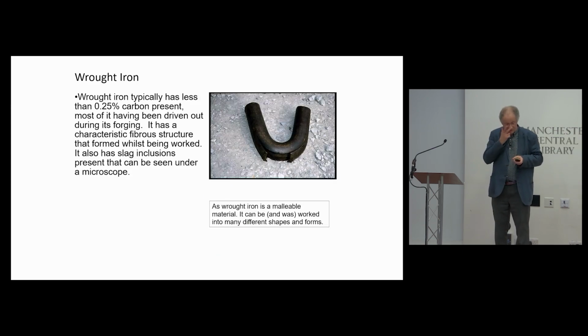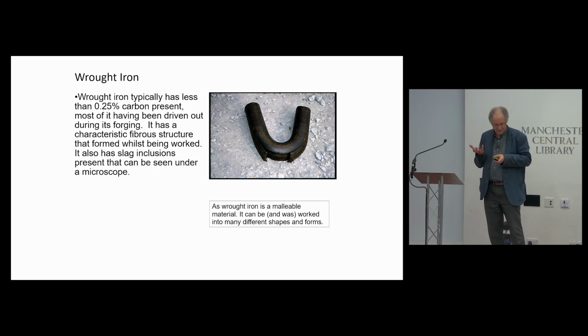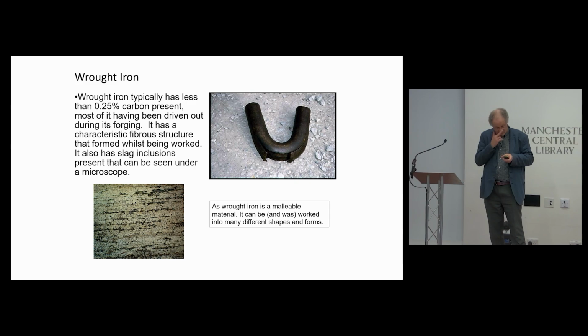So typically, wrought iron is very low carbon content, about 0.25%, as most of it gets driven out during the working process. And I'd say it's got this fibrous structure, and you get these slag inclusions in there. And there's a lot of belief that the reason that wrought iron is more corrosion resistant than steel is because these glassy materials provide a sort of seal to the metal to a certain extent. And if we look at it under a microscope, you get these straight line structures of the iron fibres with a certain amount of carbon and slag in between.